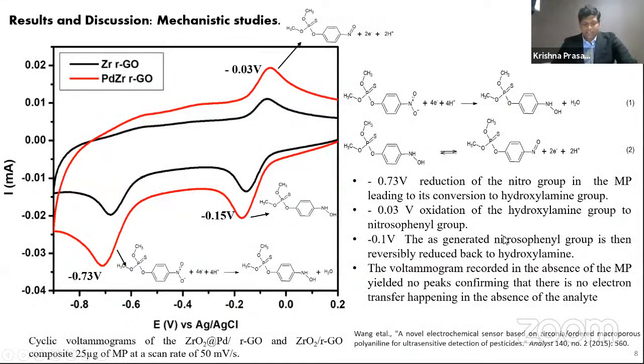And coming to the electrochemical studies, the initial response of the composite to methyl parathion was studied using cyclic voltammetry, and the drop-casted electrode was used for recording. We have found that initially there is a reduction reaction which occurs at minus 0.73 volts, and this was compared with the response previously shown by only zirconium oxide on RGO, and we found that the current generated by the PD ZrO2 RGO is much higher compared to the ZrO2 RGO composite.